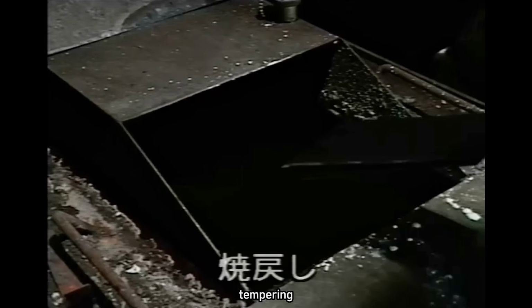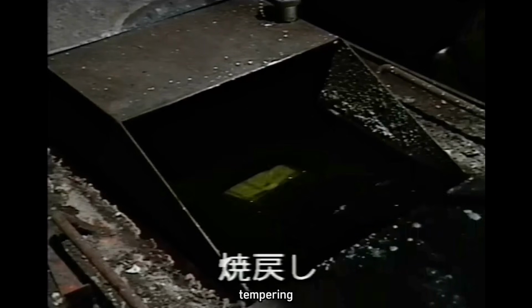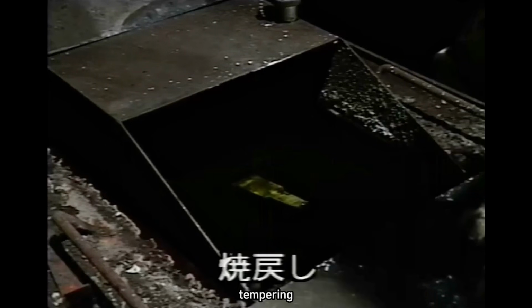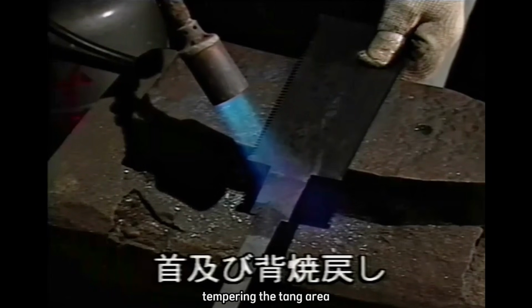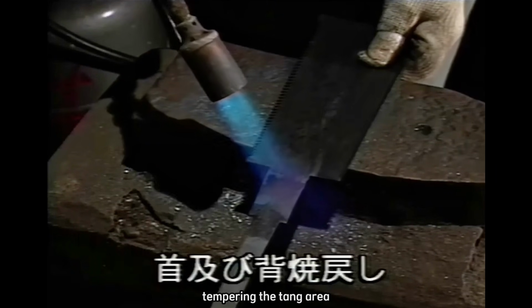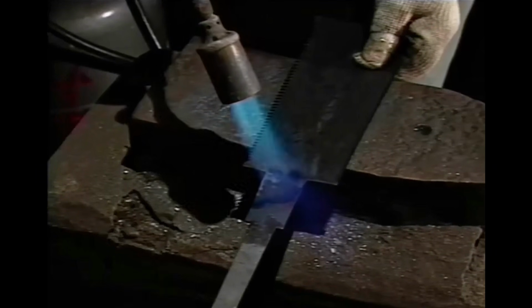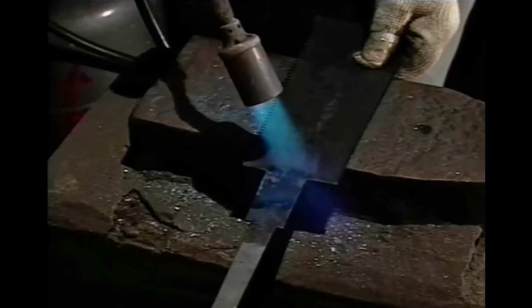The saw is tempered to the appropriate hardness for each type. Additionally, the tang area, which requires a degree of flexibility, is separately tempered. The degree of tempering is judged by the color difference.